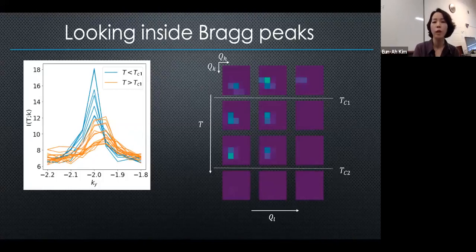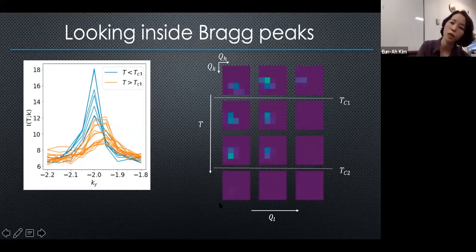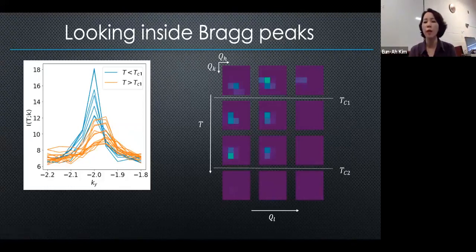And when we look at the Bragg peaks that are showing these shifts, we're able to see what happens at each of the two transitions. Now, this figure is given from low temperature up to high temperature at the bottom, which is a little unintuitive. So I want to start from the high temperature. At high temperature, there are no peaks here because the two pyrochlores were equivalent. The high temperature transition hits, and the peaks show up because unit cell size changed.